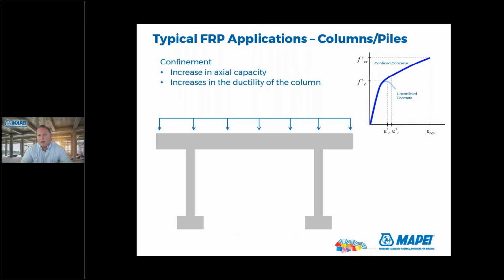And so ACI says, okay, for flexural and shear applications, those are bond critical applications. But for wrapping columns or piles, these are confinement. And so with wrapping these, you can get an increase in the axial capacity. You think like the load's coming down, the column wants to dilate, and the FRP holds it in there. So you can take a 3,000 psi concrete and cause it to act like a 4,500 psi concrete.